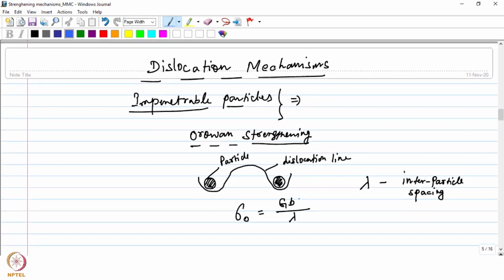Then we talked about certain dislocation mechanisms with regard to the strengthening in metal matrix composites. First, we talked about the Orowan strengthening, and this mechanism basically talks about the bending of dislocations around impenetrable solid particles, and as they do, dislocation loops will be left behind around the particles, and hence the motion of further dislocations will be hindered. Okay, and the strengthening effect is given by this particular equation according to the Orowan strengthening mechanism. Here lambda is the interparticle spacing, so it also says that as the spacing between the particles decreases, the strength will increase.